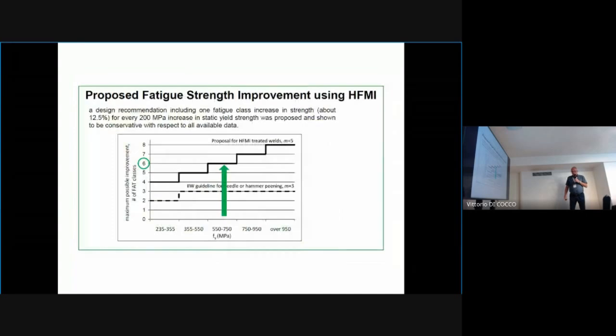The IIW recommendation says that by application of HFMI, you can use a higher fat class for classification of the weld. If the weld has this application of HFMI technology, and if you have steel with higher and higher strength, you can use a higher and higher value of the fat class. The reason is probably that in steel with higher yield strengths, you can introduce a higher compressive stress by this technology.